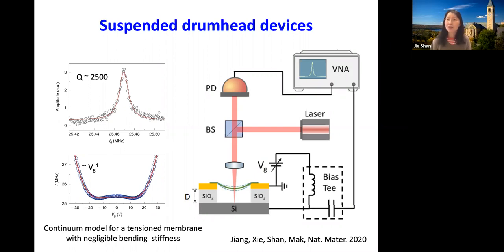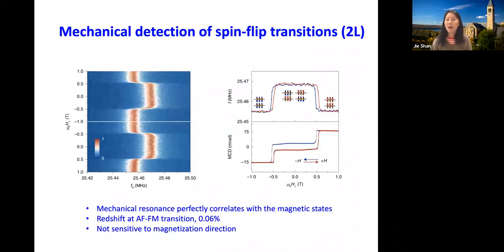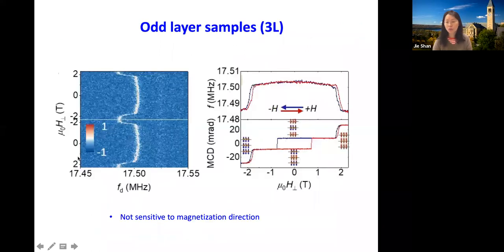Okay, so now let's take a look at the interaction coupling between spin and the mechanical properties. So now we are going to turn on an out-of-plane field. And we know that if the field is large enough, we will induce the spin flip transition. And what I'm showing here is the mechanical resonance as a function of magnetic field, changed from 1 Tesla to negative 1 Tesla, and then swept back to 1 Tesla.